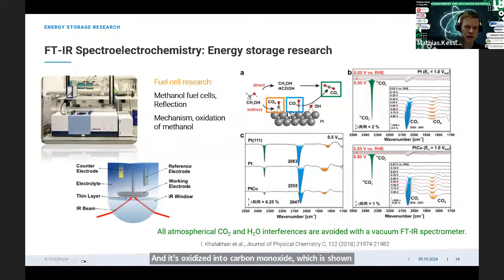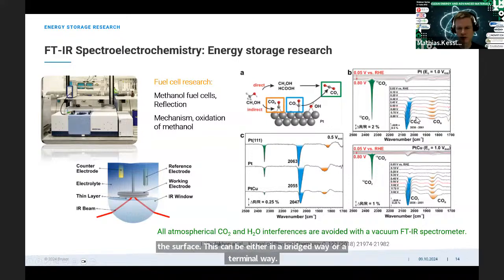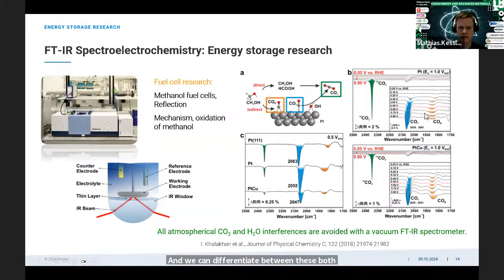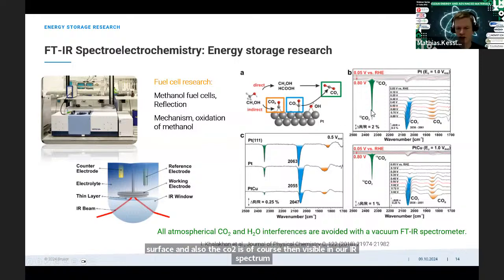And the carbon monoxide is bound in different motifs to the surface. This can be either in a bridged way or a terminal way. And we can differentiate between these two binding motifs. And then a second oxidation appears and CO2 is then released from the surface. And also the CO2 is of course then visible in our IR spectrum. And if we use a vacuum system, then we are sure that the CO2 comes from the reaction itself and it's not a contribution of the atmosphere in the lab.